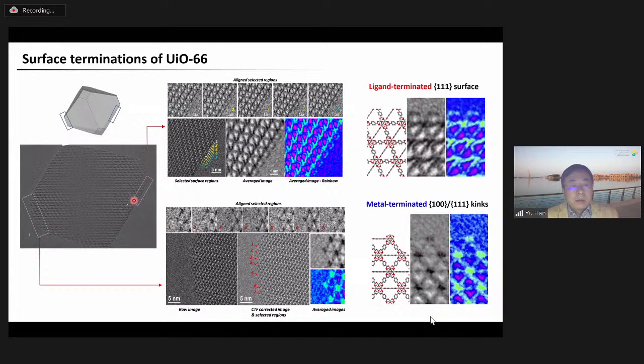The major 111 surfaces over here are terminated with organic linkers. Well, at these truncated surfaces, which consist of the 100 and 111 kinks, at these kink positions the outermost surface is terminated with metal clusters. You see very clearly here, the outermost surface consists of metal clusters without organic linkers. So two types of surface termination, organic linker terminated surface and metal cluster terminated surface, coexist in this material.